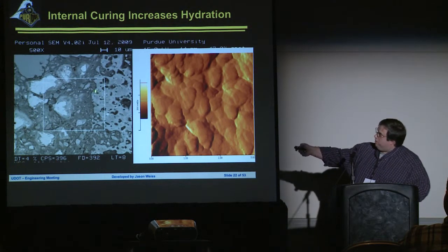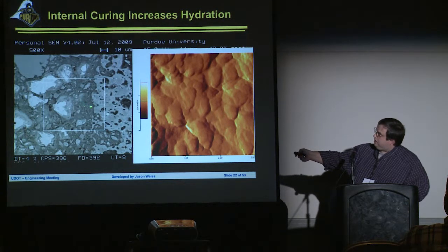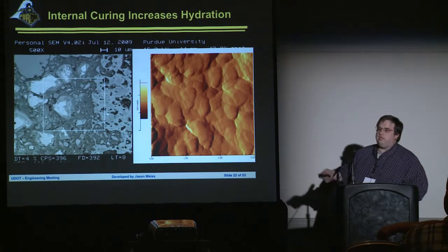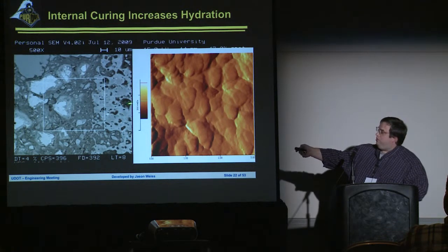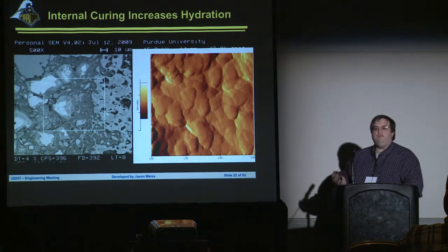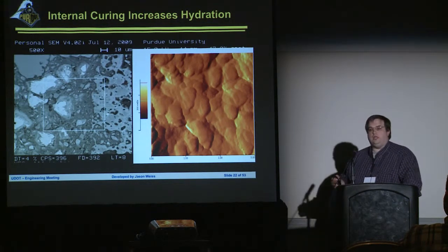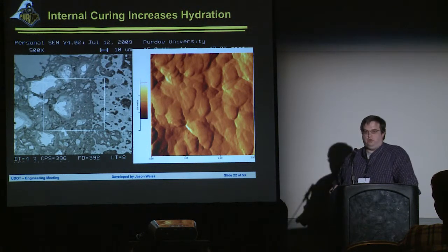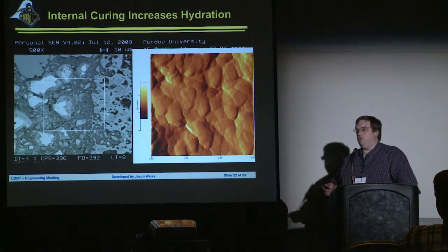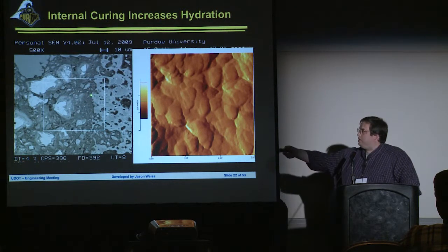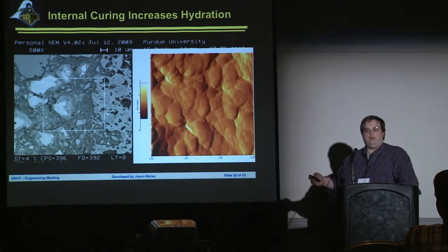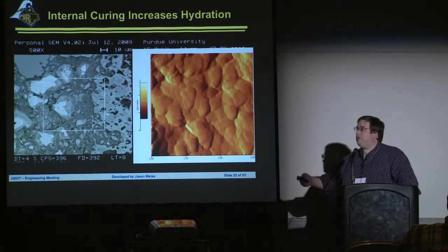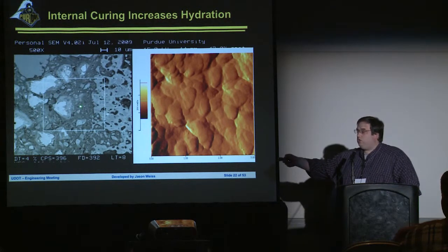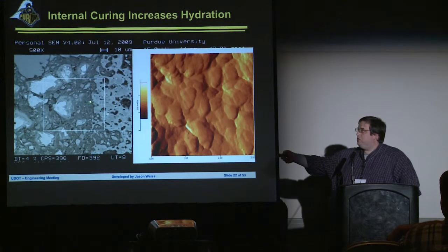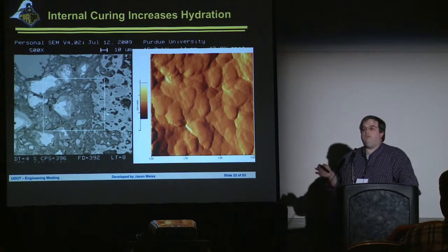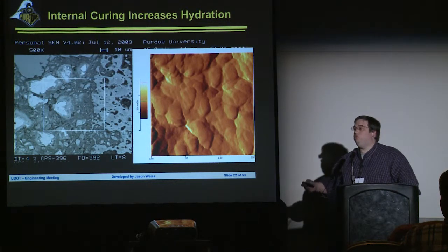This is the edge of one of these lightweight sand particles, and what you can start to see in here is we've essentially got these dark spots, which are porosity. But as water leaves these big pores in the lightweight aggregate, it fills in this matrix and makes a very, very dense matrix. Particularly, it makes it very dense at this interfacial zone. Right? This is not what we see in most normal weight aggregates. Most normal weight aggregates, we see a porous region at the edge of that aggregate. That porous region essentially allows things to transport through it much more quickly. With internal curing, lightweight aggregate, we see a very dense region here, but we also see very dense regions as we move away from the aggregate, which means it's going to be harder for things to move through the system.